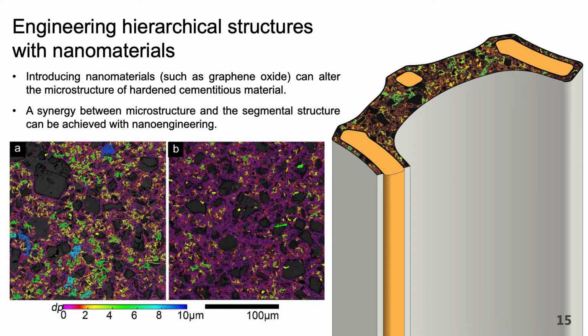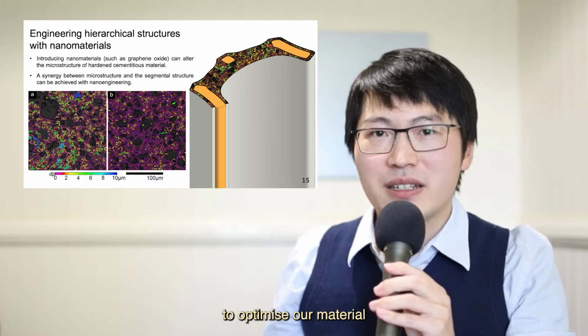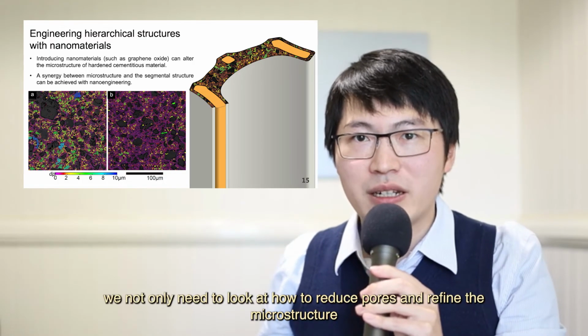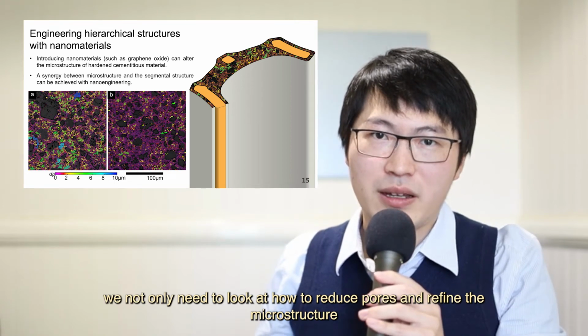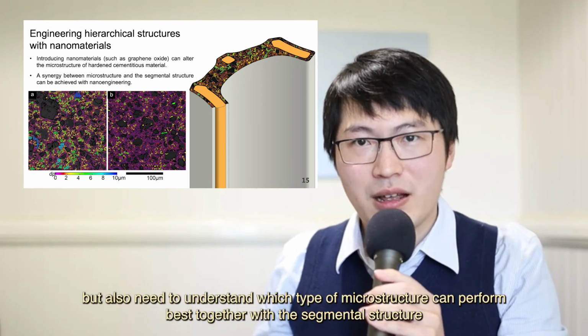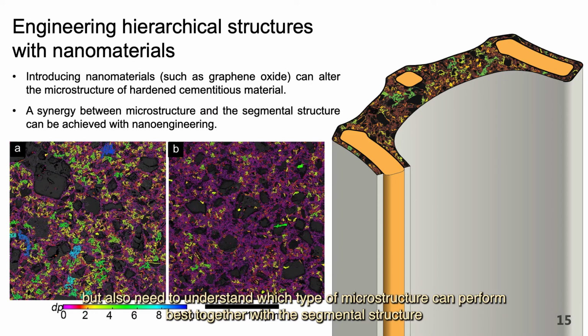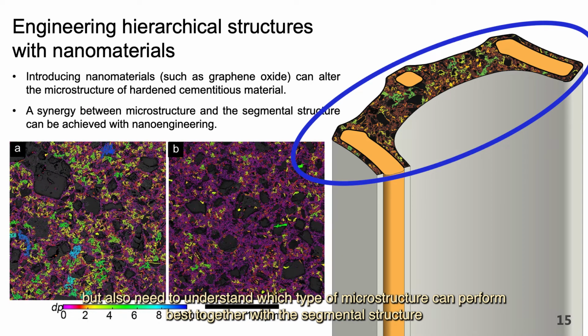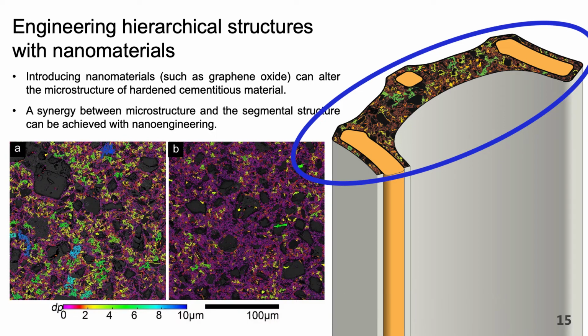Adding graphene oxide to cement paste can reduce microscale pores, which are the blue and green pores here, to nanometer pores, which are red and purple. As the pore size reduces, the performance of cementitious materials will typically be increased. However, to optimize our material, we not only need to look at how to reduce pores and refine the microstructure, but also need to understand which type of microstructure can perform the best together with our segmental structure.